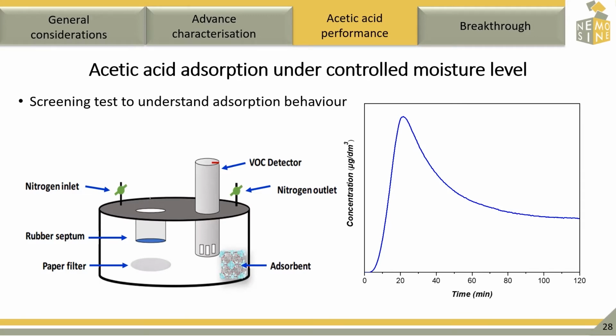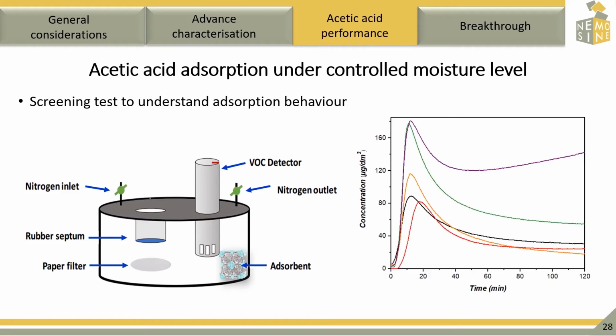This setup gives a quantitative measurement of the MOFs and provides a preliminary selection of the best materials to adsorb acetic acid under humid conditions. Here, we have some results from various MOFs tested in this setup. When we introduce the acetic acid, there is an increase of acetic acid concentrations, which originates the high-intensity peaks. And as soon as the material starts adsorbing the gas, the concentration present in the chamber will decrease. MOFs performing well will lead the concentrations down to 40 after around 2 hours of the experiment.